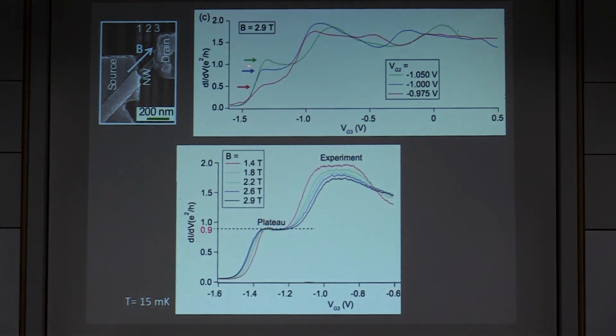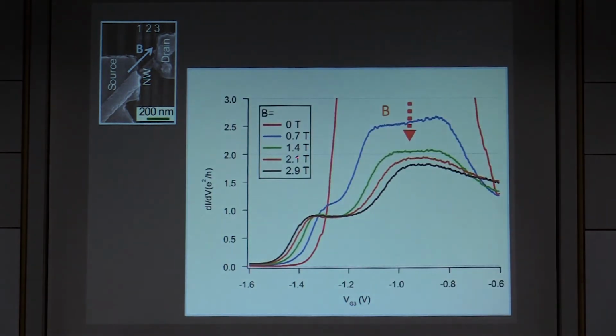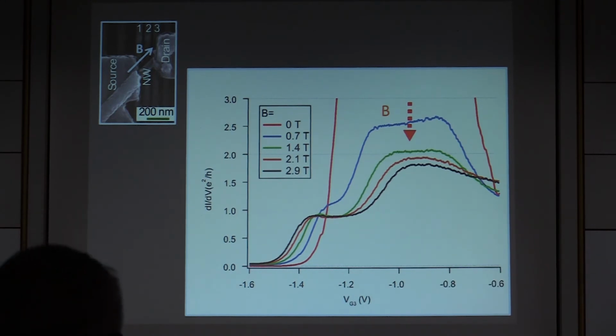But anyway, let's pick this as ideal a regime as possible and then look at the evolution in magnetic field. If I reduce the magnetic field, this plateau shrinks, as one would expect, by reducing the Zeeman splitting in the wire. I cannot go below 1.4 Tesla because, when I go below 1.4 Tesla, the contact becomes superconducting, and then the conductance overshoots. So I cannot follow my plateau anymore.